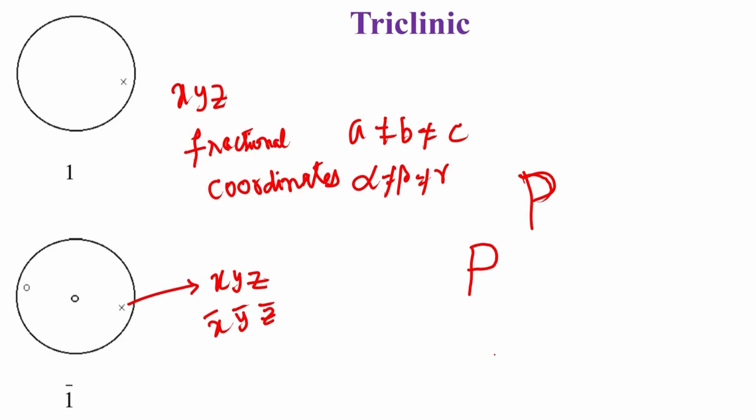So, when we write a capital P and say it is a triclinic system, it can have only 2 of the symmetry elements which can be associated with this lattice. So, the first one will be P1, and the second one will be P1 bar. So, there are 2 possibilities to combine the lattice symmetry with the symmetry that is associated with the crystal system.